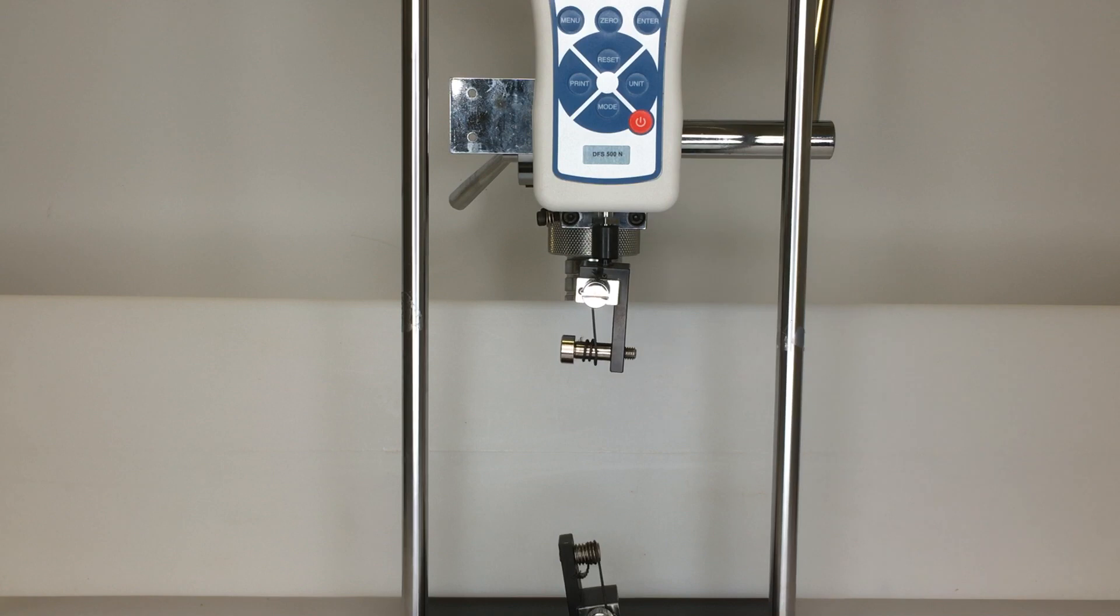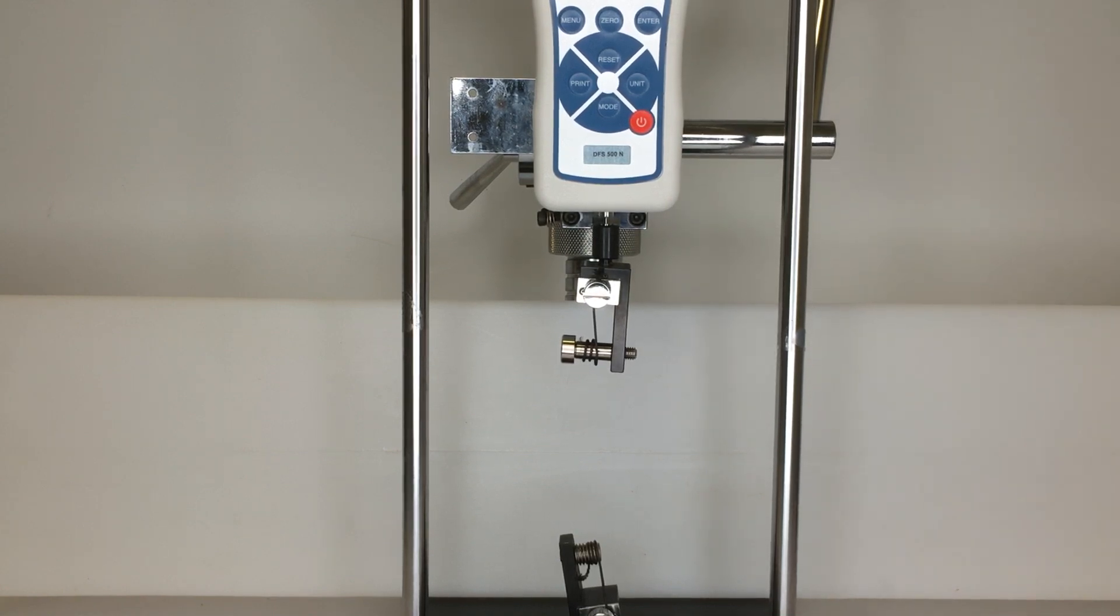You can see that it took about 82 pounds to break this carbon nanotube yarn which is equivalent to about 4 car tires worth in weight and is the strength of about 500 megapascals. Thank you for watching and please check out www.dexmat.com for more videos.